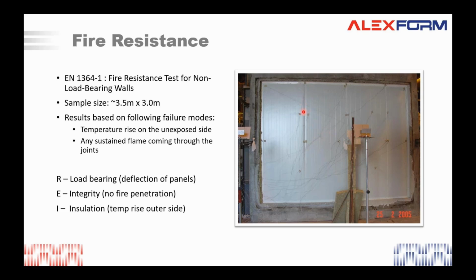And you should not see any sustained flame coming through the joints. Like we said before, the joints are the weakest point in panels. So if there's no joint, this will withstand fire forever. There's no problem. But because there are joints, the fire will deform the joints and will find a way to go through it. So the longer you delay this by sound installation practices and materials, the more fire resistance you will get. And there is another version of this where you test for the load bearing. And in that case, you also don't want to see deflection on the panels in case of fire.